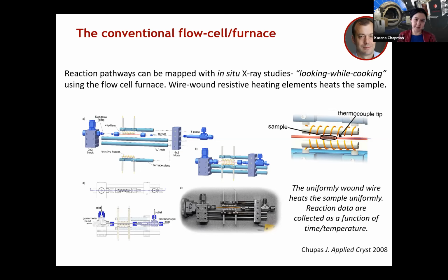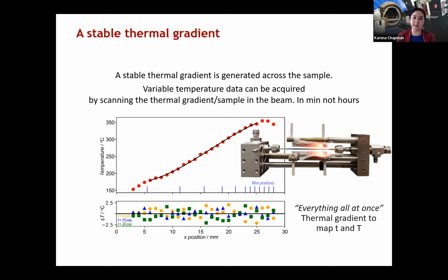And if we want to find the right temperature for a metastable phase, we really want to be able to map that important phase space across all the different temperatures as efficiently as possible. So one approach we've been taking is to parallelize this approach, instead of just looking at one temperature at a time and looking at the same reaction for 3 hours, 12 hours, as long as it takes for that reaction to progress.